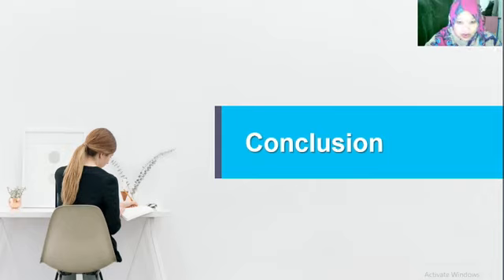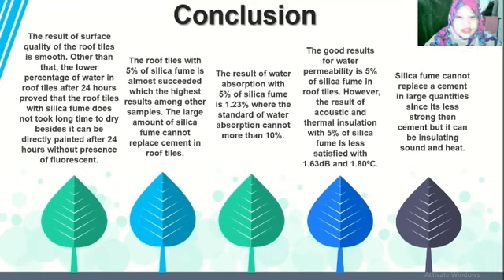Let's proceed to the conclusion. The most significant result is when the mixture of roof tiles has 5% of silica fume, as this proved to be the optimum percentage by the results. As obtained from testing, the surface quality of the roof tile is smooth. Other than that, there is a lower percentage of water in roof tiles after 24 hours. Roof tiles with silica fume do not take a long time to dry. Besides, they can be directly painted after 24 hours without the presence of fluorescence.